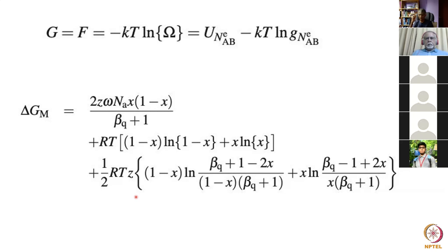Why can't we just use the empirical thermodynamics in Thermo-Calc and MTDATA and FactSage and so forth, where we have polynomials? There are cases where you cannot do that, okay? If you have an ordered system, you cannot actually talk about pairs of atoms or atoms being distributed at random. It just doesn't make sense.